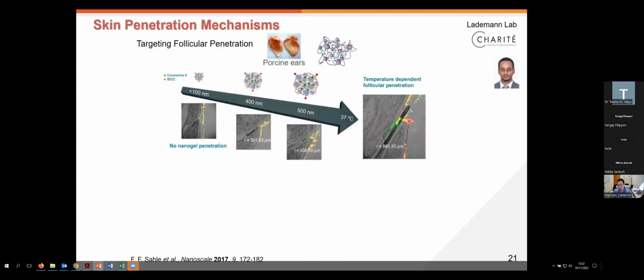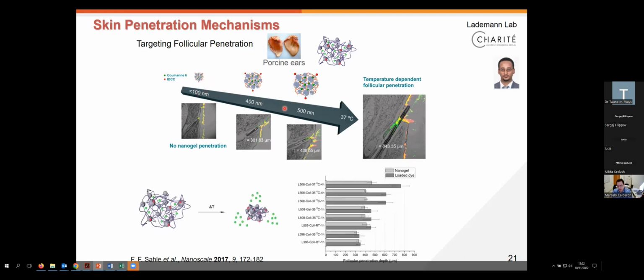And just to complete the analysis of the different potential mechanisms for drug delivery of our nanogels, together with Fitz and Sale, also from Charité, we analyzed how these nanogels could penetrate inside the hair follicles. Here we analyzed this penetration on porcine ears. And what Fitzon could very nicely see is that the penetration of our nanogels depends on their size, or the diameter they have in solution. As already reported for other polymers, it seems that when the polymer has a diameter of around 500 nanometers, it has an optimal penetration into the hair follicles. And this is what we see here when we compare the penetration of the nanogels into the hair follicles. This was also correlated with the penetration of the cargo molecule that was inside.